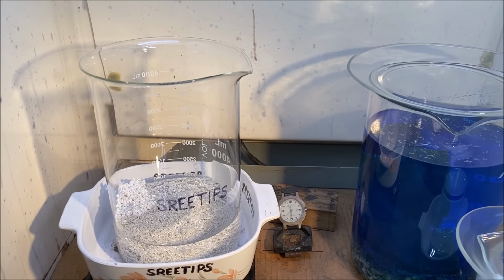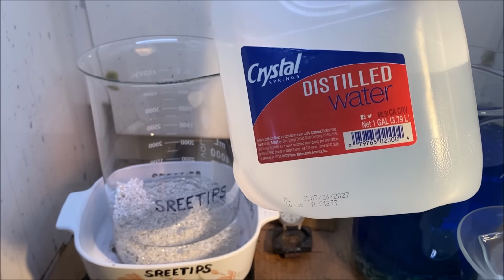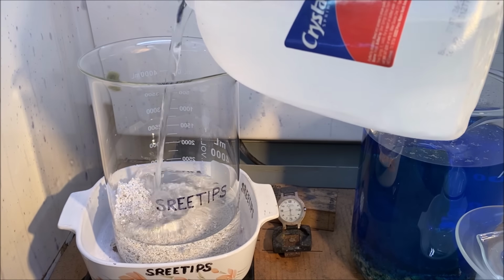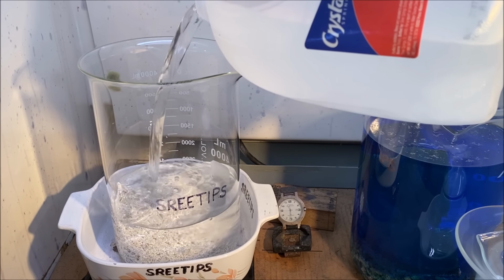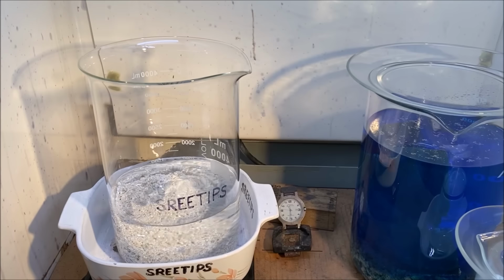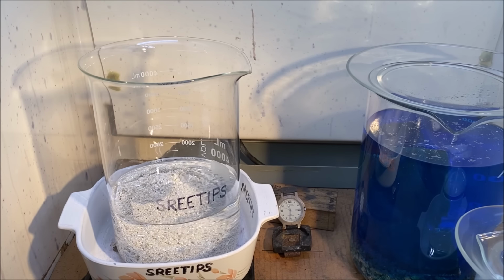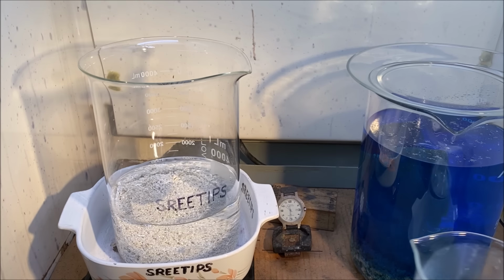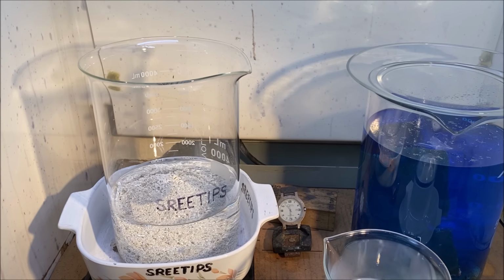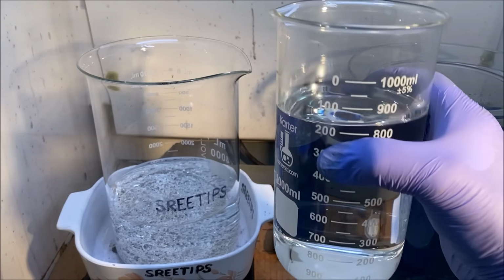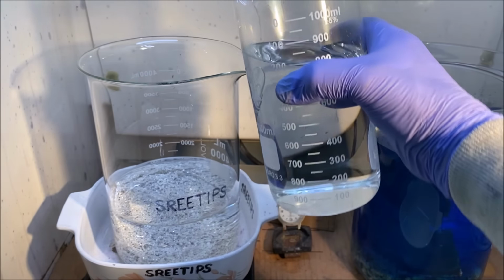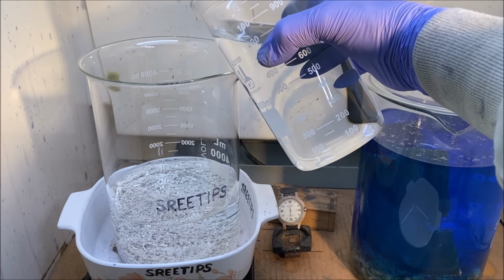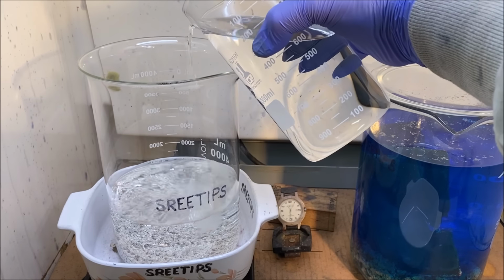Cover this up, set it back over here out of the way. I'm going to add about another 500 milliliters of distilled water to the silver in this beaker, so I put it up to about the 1.5 liter level. Now we'll go ahead and start adding some of this nitric acid into the silver and start dissolving the pure silver to make silver nitrate electrolyte for the silver cell. Here we go.